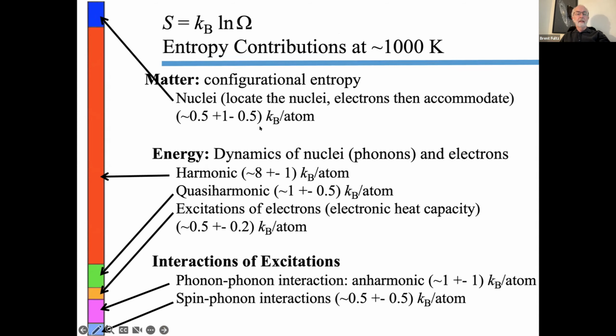but is still less than 1 kB per atom most of the time. At 1000 Kelvin, there's a large amount of entropy that you can associate just with harmonic oscillators using the ground state density of states, if you like. But as the crystals expand, their frequencies change. We call this a quasi-harmonic correction.